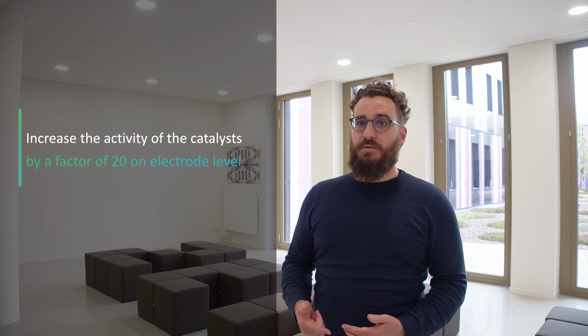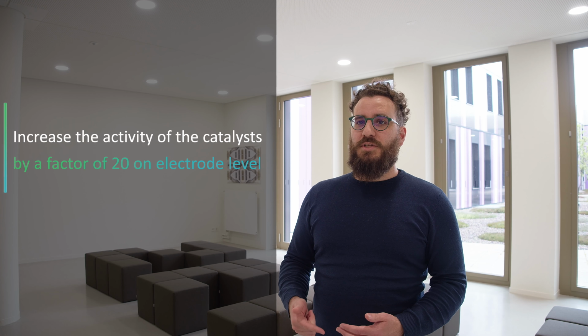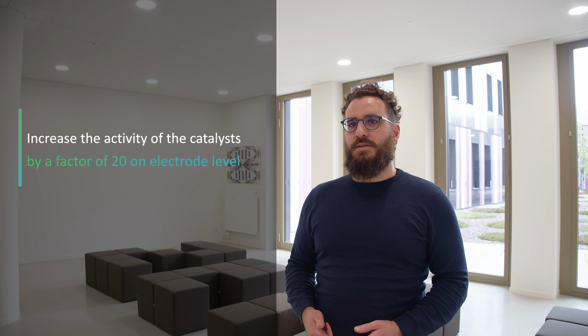The catalyst upscaling was performed by DTI at two separate stages, following the material development effort split into one CRM-rich and two CRM-reduced catalysts. DTI managed to increase the activity of the catalyst by a factor of 20 on electrode level compared to the state-of-the-art commercially available catalysts. Also, production rates of up to 50 grams of catalysts were achieved at reduced fabrication costs and material waste by utilizing a flow production method.